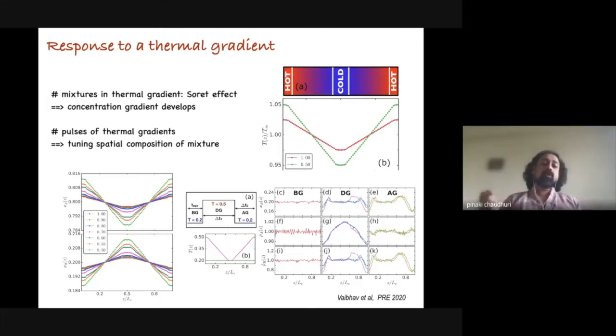So what you can do is this kind of experiment, and this is actually done in various applications. You have a glass which is at a certain temperature, and then you apply a certain pulse of thermal gradient. Depending upon the time over which you have imposed this thermal gradient, the current will start flowing through the system, and these A particles and B particles will also start moving towards these preferential zones, either towards the hot end or the cold end. And on the bottom right corner, we have a